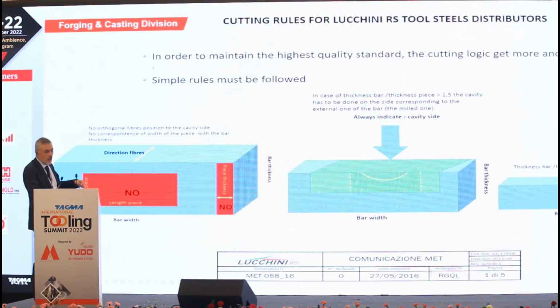Always it is important to mark on the surface of the block for the tool maker the surface from which to start the operation of machining to manufacture the die. And never, the ratio between thickness of the block and thickness of the piece can be more than 2 to 1. Okay? If I have a block of 500 millimeters thickness, it's better to avoid slicing a thickness of 100 millimeters from such a big block for a die.